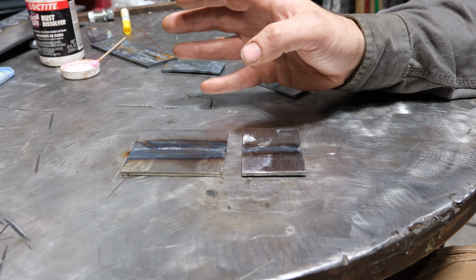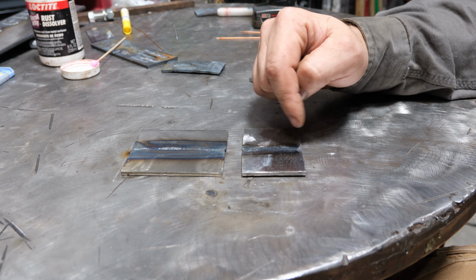I'll put up some arc footage right now of slowing down with a fusion weld over this, and let's look at it. So to start things off, we're going to run this weld fairly slow, and don't worry, I'll do a direct video comparison between this weld and the one earlier where I basically ran too fast. But the puddle here is getting pretty wide. It's about 4 electrode diameters, so I'm using 1/16 filler, so 1.6 millimeter filler. It's somewhere around 1/4 inch wide, and this is perfectly acceptable.